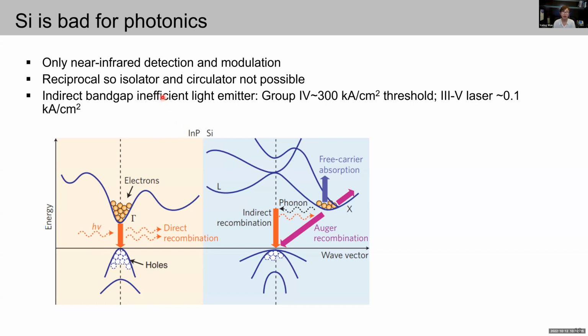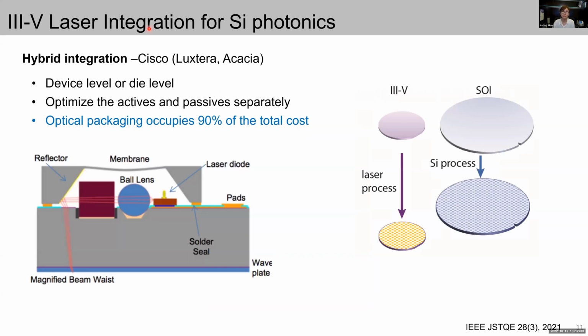As a result, to overcome the inherent limitations of group 4 materials for gain, efficient modulation, and detection at wavelengths outside the near infrared requires that we integrate III-V materials together with the silicon photonics platform. Given that lasers were the primary missing component in the silicon photonics platform, III-V and silicon integration research has been focused on generating efficient lasers. To integrate III-V lasers onto the silicon substrate, the first generation is hybrid integration. Basically, people fabricate the III-V device and the silicon device separately, and then mount the III-V dies on top of the silicon photonics dies using external coupling. One obvious advantage of hybrid integration is the capability to optimize the active and passive parts separately without sacrificing process compatibility. However, this kind of optical packaging with optical alignment often occupies over 90% of the total cost.